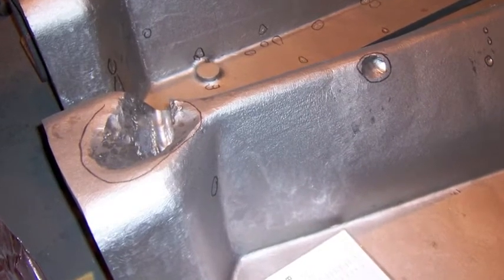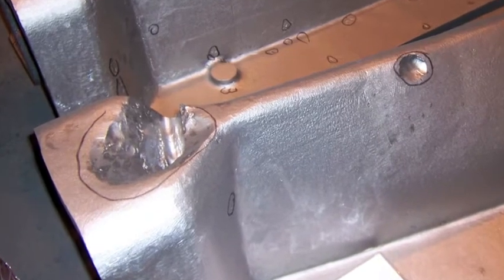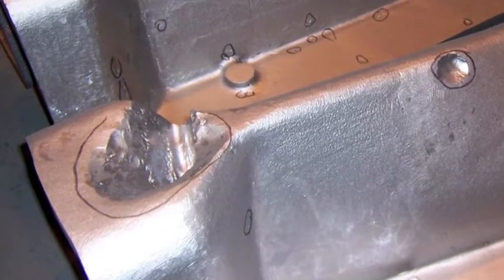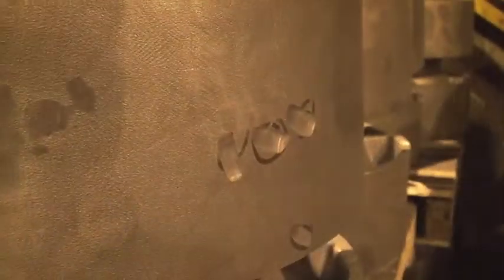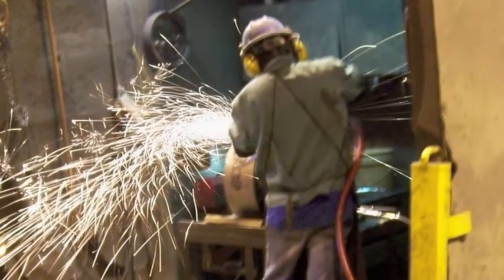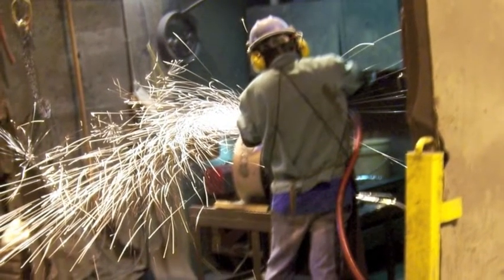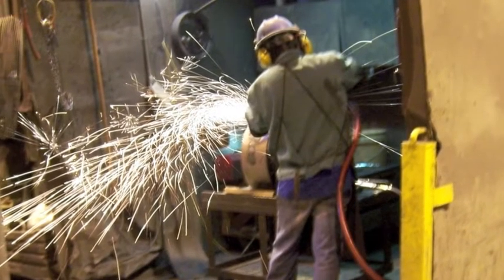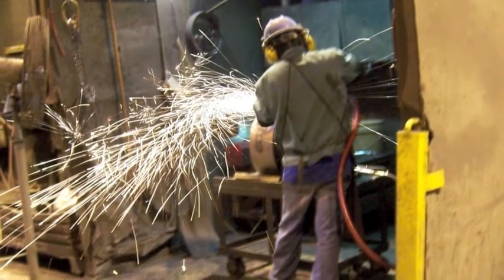Inclusions are process defects resulting from multiple sources of variation. Here, you can see cast metal parts with clear, pitted surface defects. These surface inclusions are caused by either oxidation of metal during the pouring process or from sand flaking away from the mold cavity. Once these surface defects are identified, they are ground down and then filled with welding material. All of this is considered rework, and our semester project was primarily focused on reducing inclusion occurrence rates.